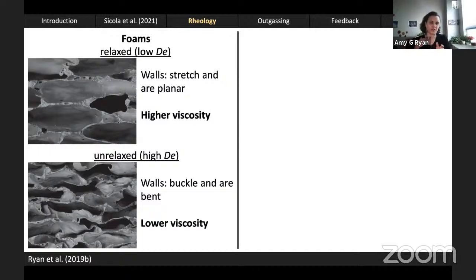In contrast, when the melt is relatively unrelaxed and it's being deformed, it doesn't really have the capacity to respond quickly to deformation. And as a result, the bubble walls just sort of buckle and bend. And the moment that buckling happens, it actually makes the material softer and softer, and you get a runaway effect, which is that strain weakening that I saw in the mechanical data. At some point, the bubble walls can't buckle and bend any further without starting to touch one another, and that's where the strain hardening kicks back in. But overall, this shape of the bubble walls makes the material quite soft, and that's evidenced again by the low effective viscosities measured relative to the relaxed foams.